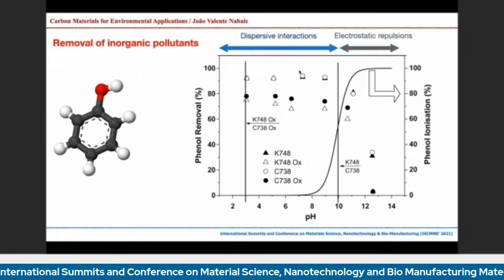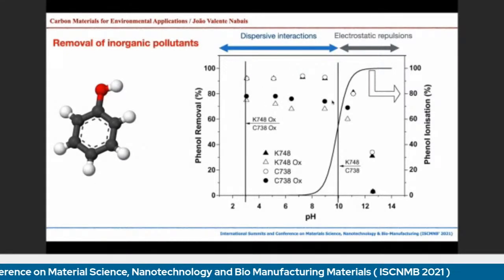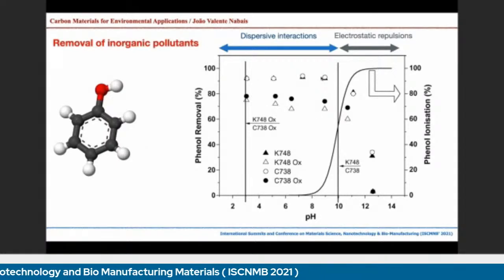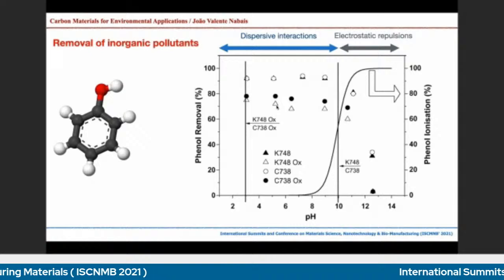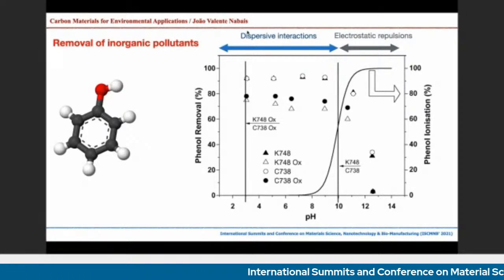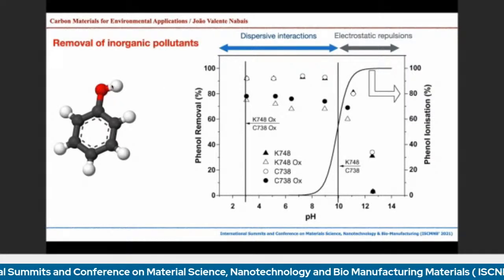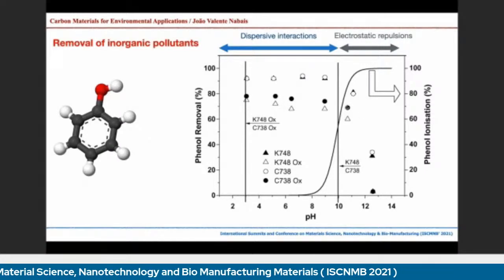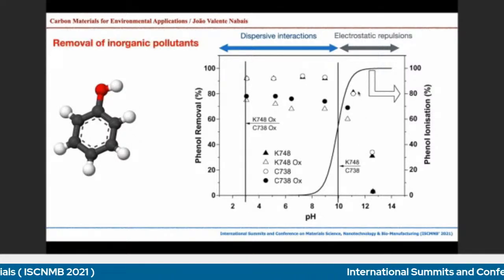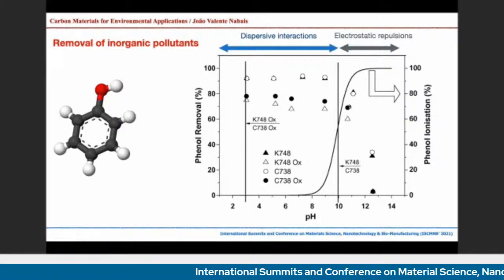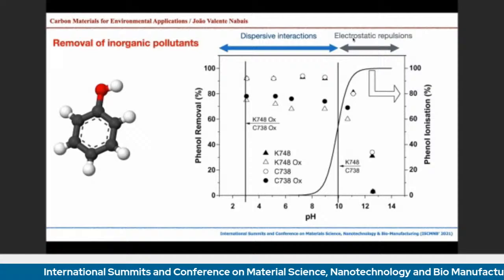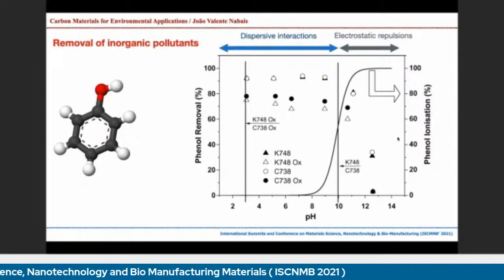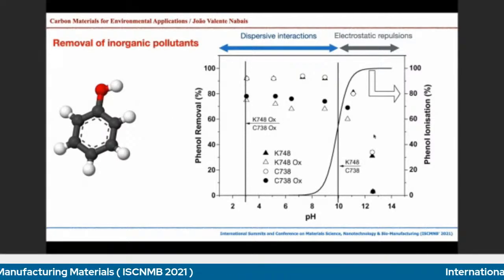You can see here in this area that no matter the charge of the carbon, the adsorption does not vary that much, which means that in this area what promotes the adsorption is the dispersive interactions. But then when the phenol starts to be ionized, which means that the phenol molecule will acquire a negative charge, the adsorption will decrease significantly. What does it mean? It means that in this area, the driving force for adsorption is no longer a dispersive interaction, but electrostatic repulsion, because both the molecule of the phenol and the surface of the carbon are negative, so they repel each other.